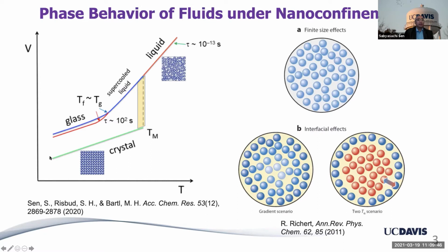So this is a volume temperature diagram that is well known among, at least, very well known among glass scientists because we look at it almost every day, which is that when you take a liquid and cool it, its volume decreases, density increases, and it has two options. One is that it can suddenly undergo a first order transition to a crystal, which is shown by this vertical dashed line.